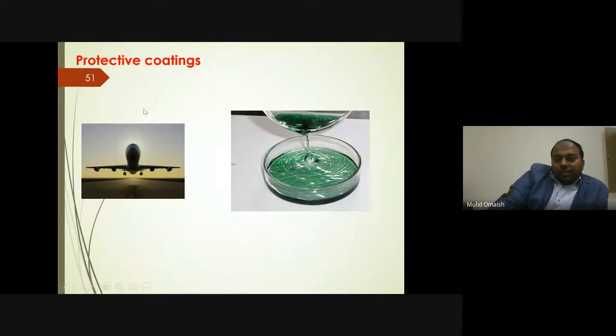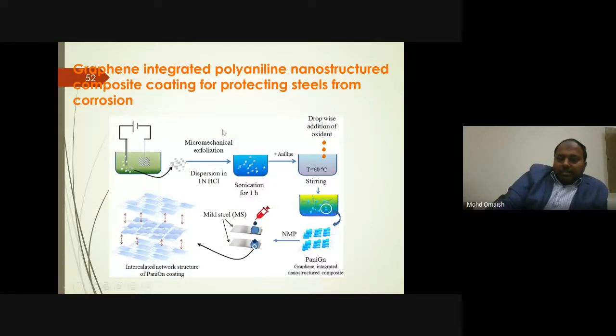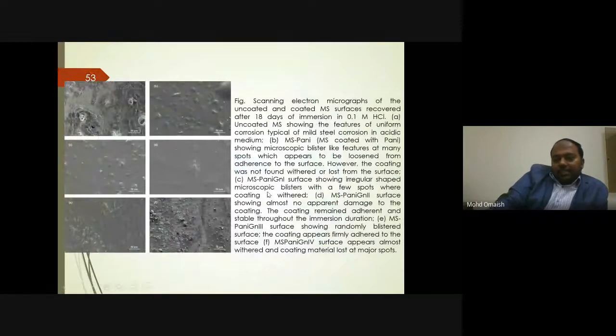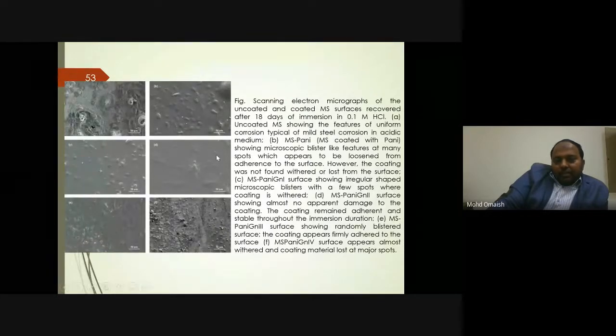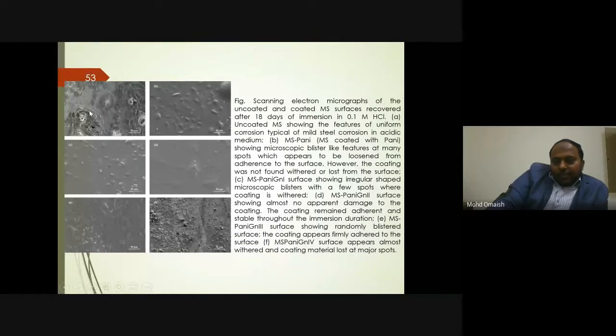Another application of polyaniline is in protective coatings against corrosion. For this, polyaniline or polyaniline-based composites are generally dissolved in some solvent, and they can be coated or sprayed on steel or iron, and after that corrosion studies can be done. This is one of the results, and this is the bare steel surface. In HCl, it is highly corroded, but in the case of polyaniline, the corrosion